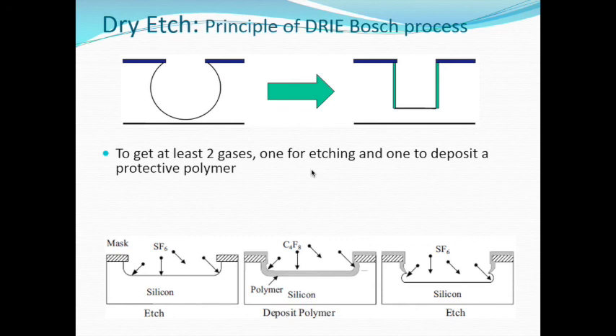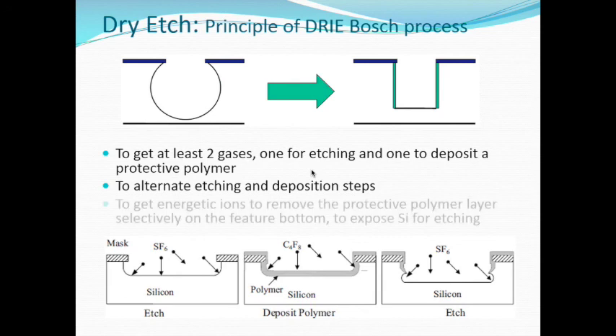You can alternate the etching step and the deposition step here. Also, you have ion bombardment to the bottom to remove the bottom polymer layer here. Look at it this way. What exactly is happening here? You start with the etching chemical, the etching gas here, so you make this profile, and a few milliseconds afterward you deposit here, and then you etch directly to the bottom part, and then you repeat this again. So you do etch, deposit, etch, deposit, etch, deposit, and gradually you get this profile.